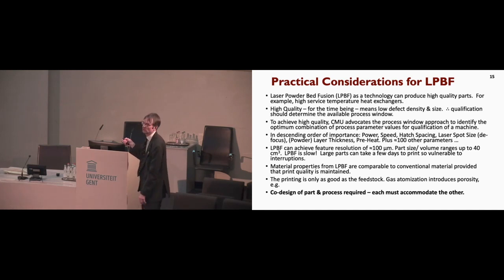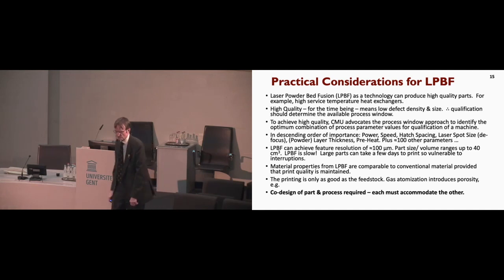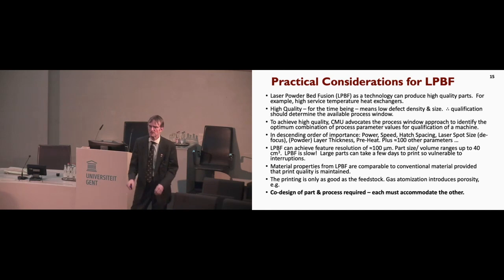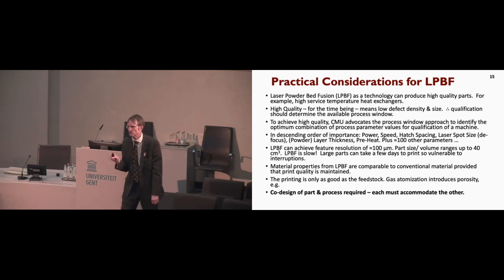And so we've arrived at a certain sort of hierarchy of process parameters. And the ones that we know are crucially important are power, scan speed, hatch spacing, laser spot size, that's not so generally known, and some others. And you will hear a lot of stories about, oh, you should be looking at this or that aspect. They're not wrong, but you do need to start in the right place. Resolution. The typical laser powder bed machine can get a spatial resolution of about 100 microns, which is pretty good when you think about it. And you can do a little better than that in certain machines.